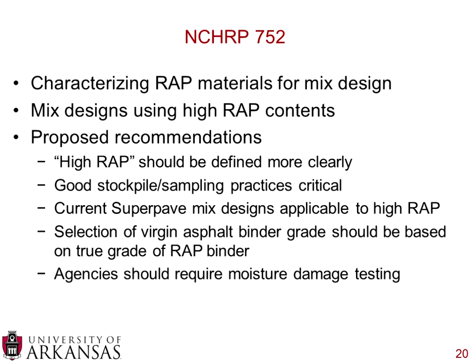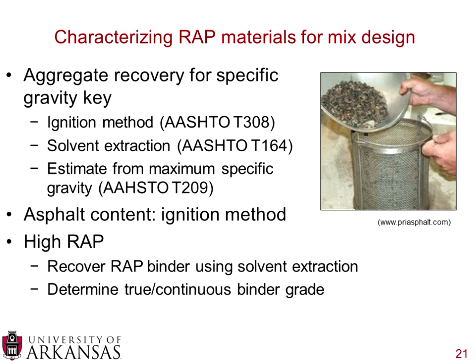And again, we've heard a couple times already, but talking about the concept of the RAP not getting as much drying as the virgin aggregate, moisture damage is definitely a concern. So when you're thinking of characterizing the RAP materials for mix design, they believe that the specific gravity of the existing RAP aggregate is absolutely key, especially when you start getting to the higher RAP content amounts. And they identified three ways that you can recover the aggregate for the specific gravity.